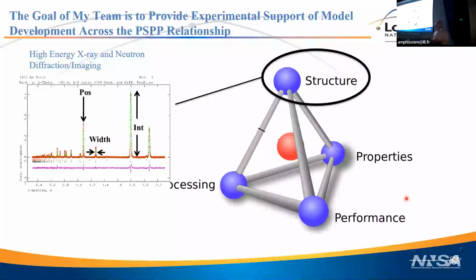We use neutrons and or high energy X-rays because they give us a window into the inside, into the bulk of the microstructure. Both will penetrate materials to macroscopic distances, and that's what's valuable. We will collect diffraction and pull certain parameters out of the diffraction pattern, things like the peak intensity, the peak position, which tells us how far the atoms are away, and the peak width, which might tell us about heterogeneities. Now, the real trick, and I'll go into a good bit of detail about this, is how you separate all the microstructural features that contribute to, for instance, the interatomic spacing.